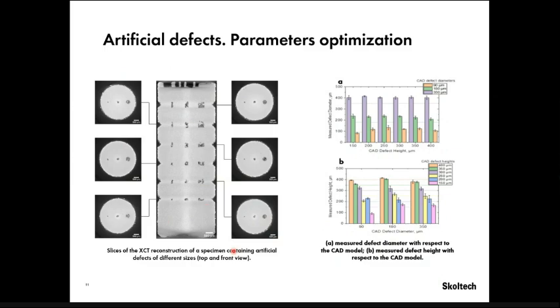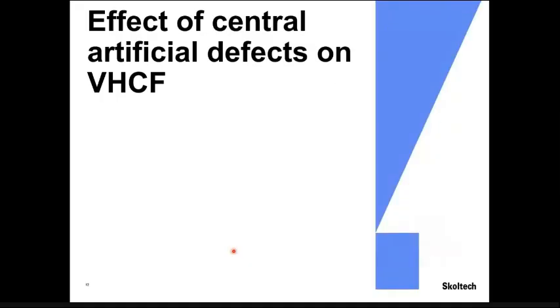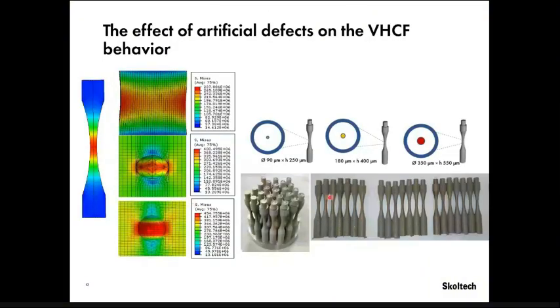And to understand how the CAD relates with the reality, it brings us to the testing. Actually, we insert these artificial defects in our very high cycle fatigue specimens. These are as-built specimens, but we machined them before testing. So we inserted the artificial defects in the very center of the specimens, and we chose 3 sizes.